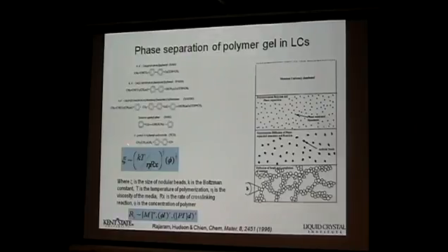So I think the size of this nodular beads or whatever fibrils you call this is a function of the temperature. Certainly the viscosity controls the diffusion limit. So this is also the reaction rate, the phase separation rate that we discussed yesterday. And then it's also proportional to the concentration. So the size of this is inversely proportional to the rate of phase separation.